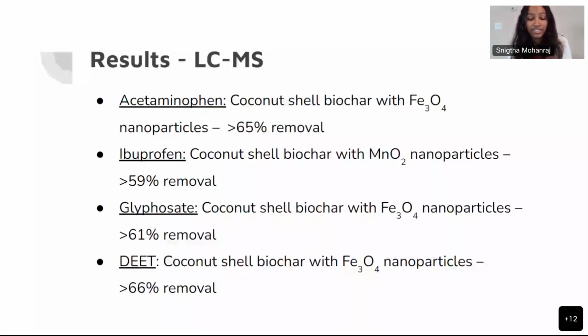And so in the LCMS, the first analysis, it was shown that acetaminophen, glyphosate, and DEET had the highest removal rates through using coconut shell biochar with iron oxide nanoparticles, removing over 60% of contaminants. The ibuprofen's most efficient removal rate was achieved through using coconut shell biochar with manganese dioxide nanoparticles. However, with the iron oxide nanoparticles as well, there were high results yielded as well.